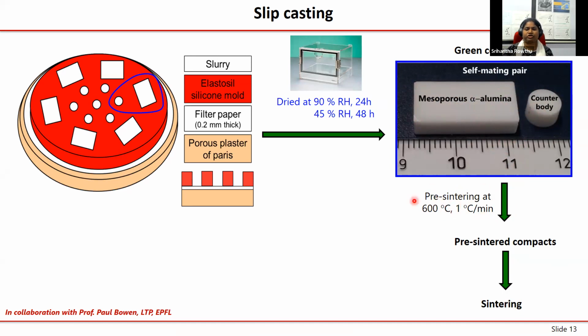Therefore, first of all, we'll do a pre-sintering step at 600 degrees Celsius. We'll heat from room temperature to 600 degrees Celsius very slowly, that is 1 degree Celsius per minute. At 600, we hold it for 1 more hour and let it cool in the furnace. So the pre-sintered compacts are obtained after we remove all the organic binders. Now from the pre-sintered compacts, we do a conventional sintering in air, because it's an oxide, so it's okay to do it in air. Sintering is done at different temperatures so that we can control the porosity of the specimen.